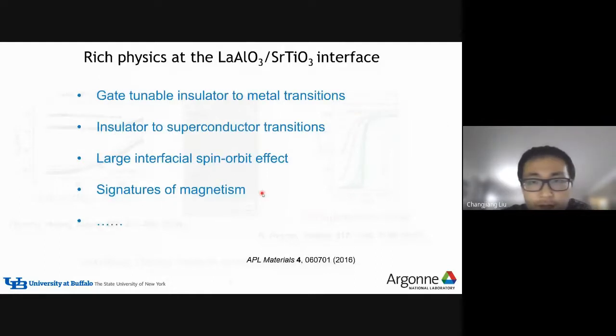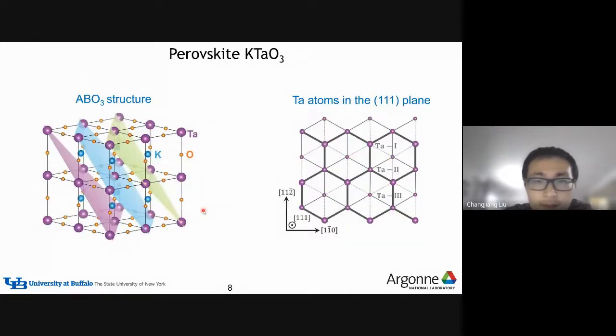Turns out that this interface can show actually quite diverse properties, such as gate tunable insulator to metal transition and insulator to superconductor transition. So large interfacial spin orbit effect. And people also found signatures of magnetism at this oxide interfaces. So the material I was focused on is also basically perovskite, potassium tantalum oxide. So this material actually is very similar to strontium titanium oxide.